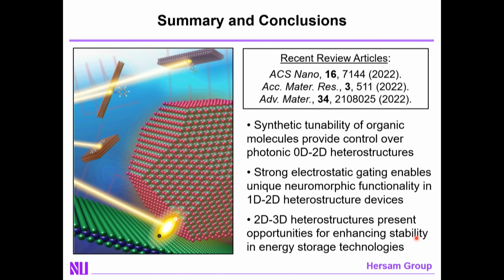All right, with that, I think I'm out of time, so let me quickly conclude. I tried to make 3 points today. The first is that the synthetic tunability of organic molecules provides control over photonic 0D, 2D heterostructures. Secondly, for 1D, 2D heterostructures, the opportunity is to exploit asymmetric electrostatic gating to achieve highly nonlinear neuromorphic responses. And finally, in the 2D, 3D heterostructure realm, we're using the 2D material as a coating or a stabilizing agent, which improves stability for energy storage technologies.